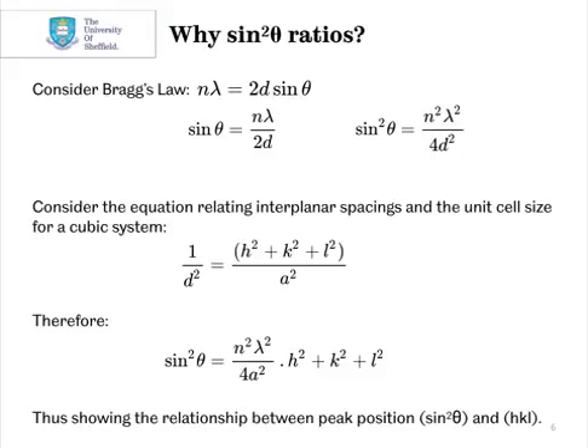We can also consider the equation that correlates the d-spacings between planes in a lattice and the unit cell size for a cubic system: 1 over d squared equals h squared plus k squared plus l squared all over a squared. Combining these 2 equations gives us sine squared theta equals n squared lambda squared over 4a squared multiplied by h squared plus k squared plus l squared. This n lambda section effectively becomes a constant, and so we can ignore that for the time being. So what you can see is there's a direct correlation between the position of the peaks in sine squared theta and the Miller indices h, k, l.